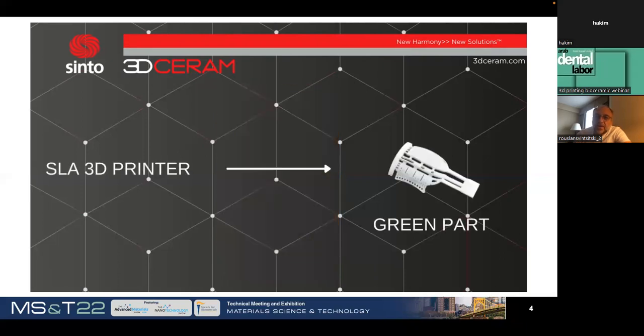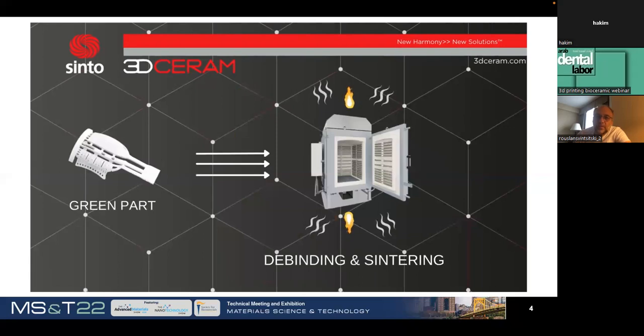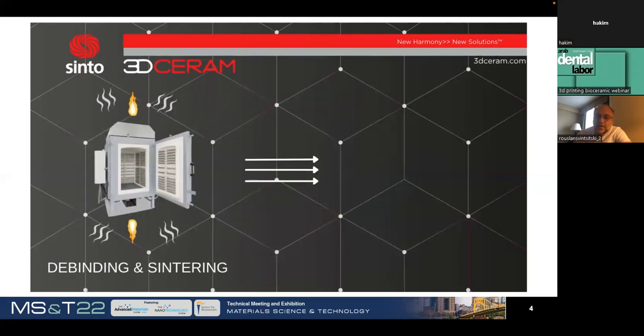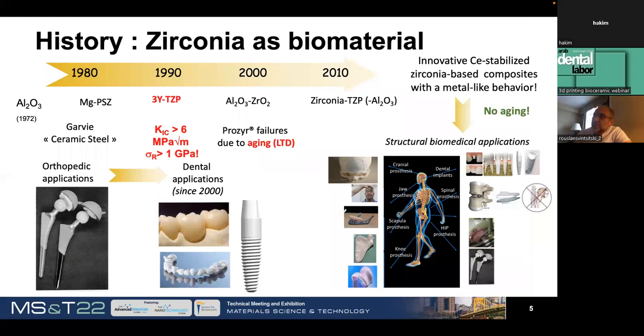Because the 3D printing is just the first step of the whole process. When you have the green part, you clean it, you have to debind it and to sinter it. And only after sintering, you have the ready to use part. Here you have the example of the foundry core used in investment casting, but it can be dental crown, it can be dental implant, it can be skull implant, etc. So debinding and sintering allows debinding to remove the organic material, so this binder which was mixed with the ceramic powder, and the sintering welds the particles, ceramic particles between themselves to give these final properties to the ceramic materials.